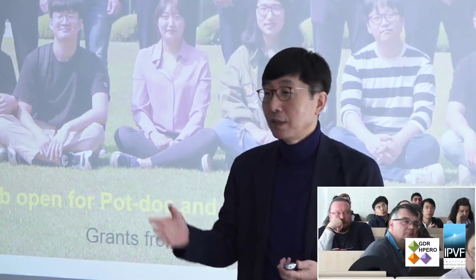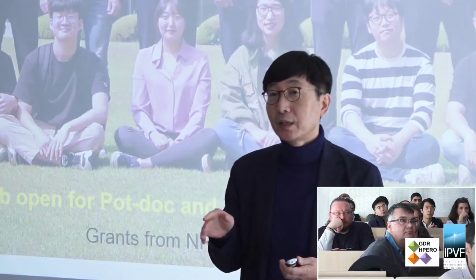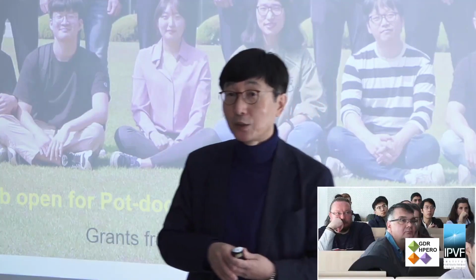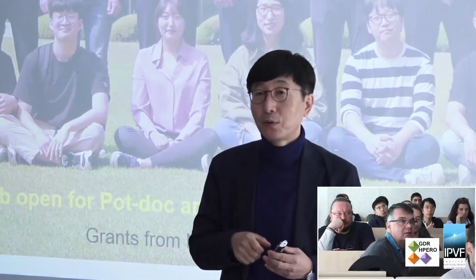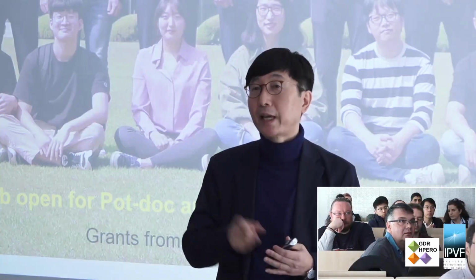And also I would like to mention that the perovskite will decompose into methylammonium iodide and lead iodide, and the methylammonium iodide will be evaporated as the gas methylamine or something like that. But the PbI2 in pure water has a solubility product of 10 to the -8. It is hard to dissolve in water. So this is also good news. But anyway, from my personal point of view, we have to find a way so that the lead 2+ is not released to the environment, by developing recyclable technology.